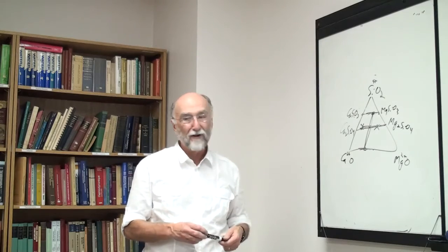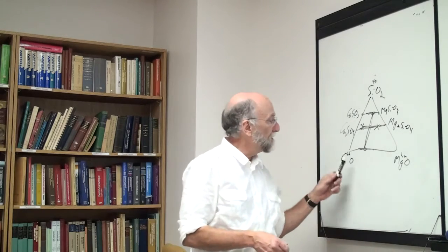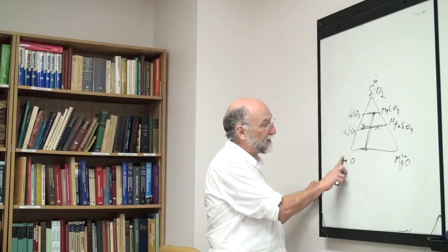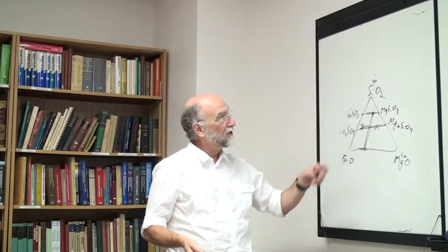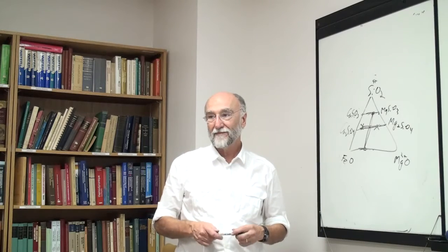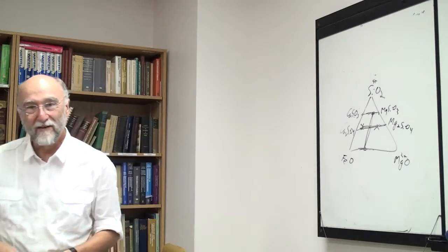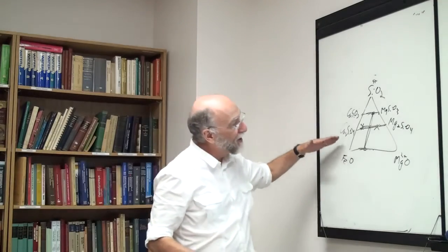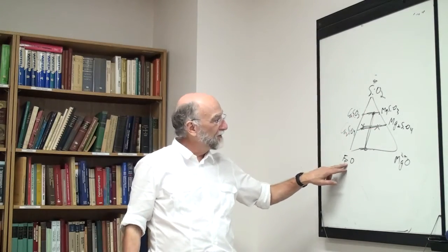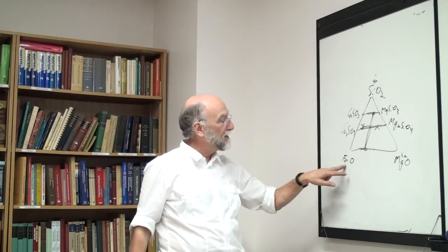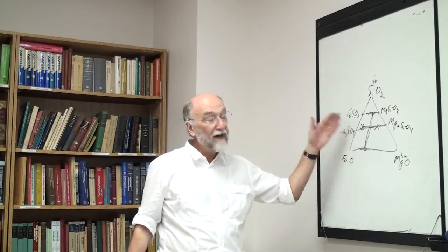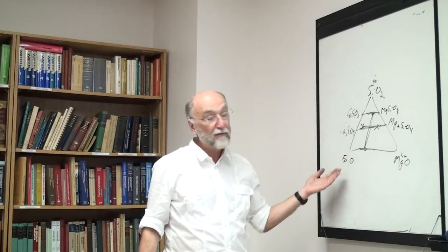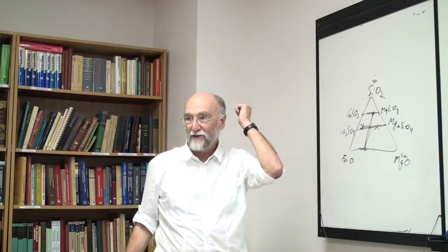At least when you look at it, you can figure what's going on. Certainly if you have two oxidation states, though, people make that mistake. You'll see FeO, and it's not. Now that is a quasi-ternary diagram if you fix PO2. But that's another story. That's very much like the iron-nickel-oxygen one. If you fix PO2, you can't write FeO-MgO because this won't necessarily be FeO. It'll vary between FeO and Fe2O3, but it still will obey the rules of a ternary diagram because all phases have to be at the same PO2. If that makes any sense.